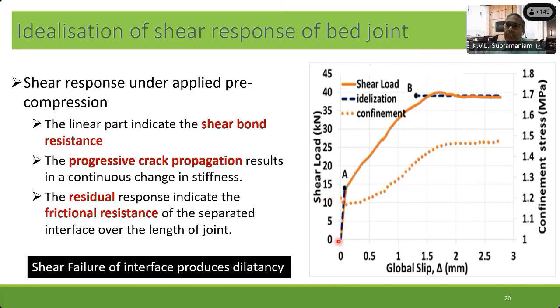That is when, before this test starts, the slip is 0. Then when I start pushing the middle brick, you see the slip starts to increase. Slowly, the middle brick starts to move relative to the other two bricks. As that happens, the shear load actually picks up. Initially, what you see is a nice linear response.